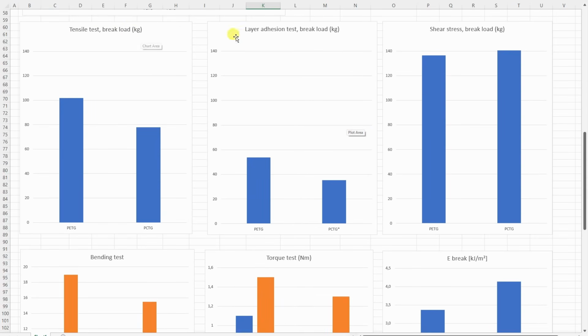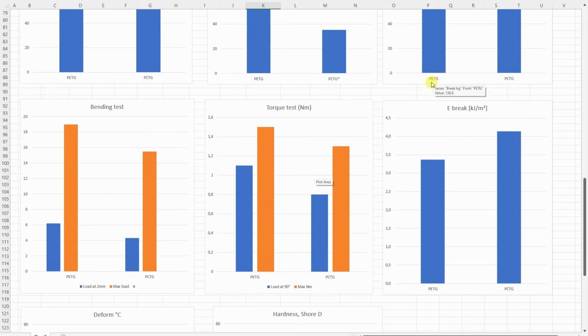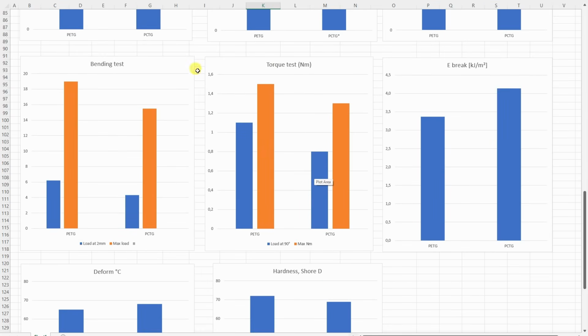On tensile test, layer adhesion test, in both cases the PETG was better, at least 20% maybe. On shear stress I got very equal results. Usually on bending test and torque test I got very similar results, and in both cases the PETG was better, approximately 15%.